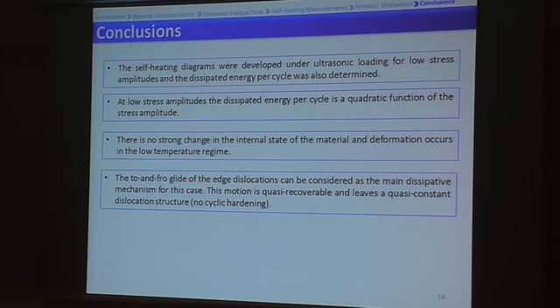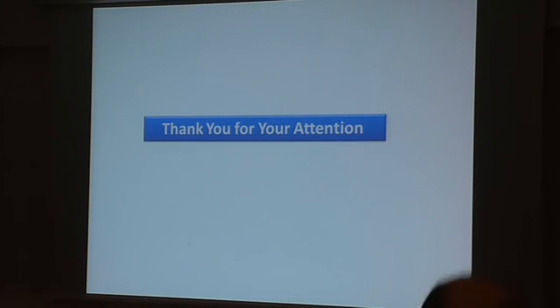So in this work, we obtained the self-heating diagrams for our material, the DP600 steel, under ultrasonic fatigue tests. We observed that at low stress amplitude, the dissipated energy is a quadratic function of the stress amplitude. Moreover, we concluded that there is no strong change in the internal state of the material, and deformation occurs at low temperature regime. And finally, we observed that the to and fro glide of edge dislocations can be considered as the main dissipative mechanism in our case, with no cyclic hardening. Thank you for your attention.